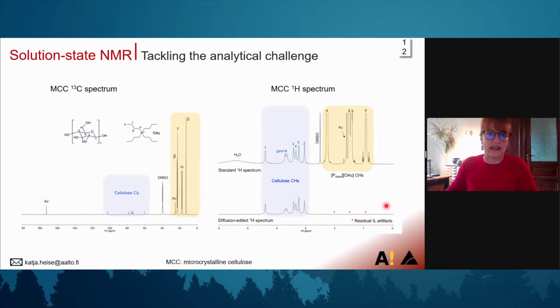And how does this look like? So this is a carbon spectrum on the left side of microcrystalline cellulose. And as I said, the ionic liquid signals are nicely outside of the range of our cellulose backbone signals, which are also nicely resolved. If we go to our proton spectrum, we see the same thing. So we have here the standard proton spectrum on top, which has nicely resolved backbone signals.